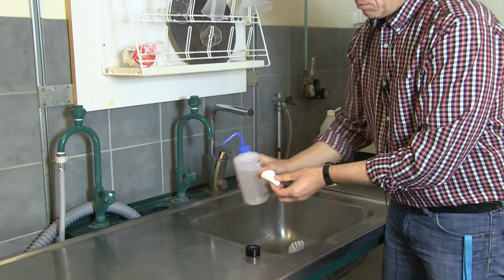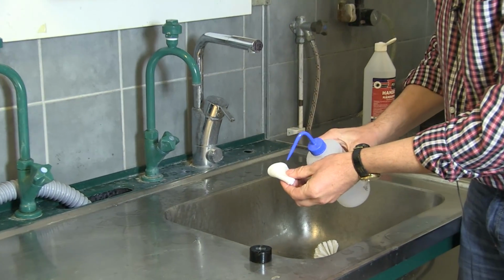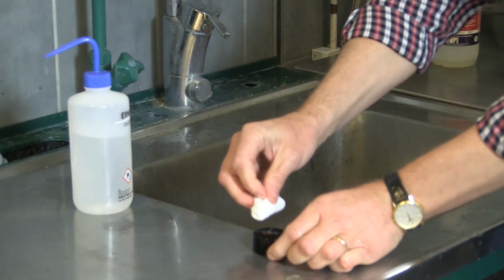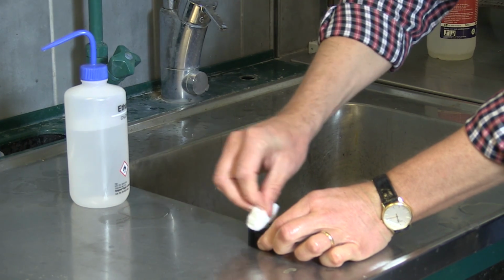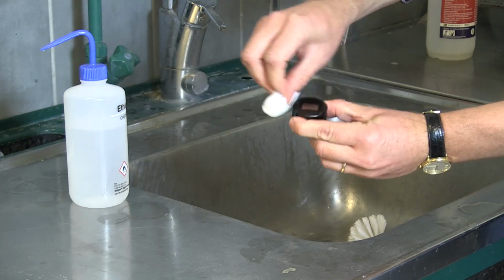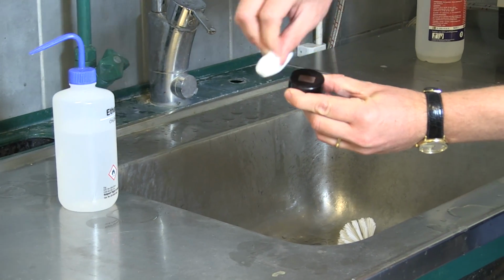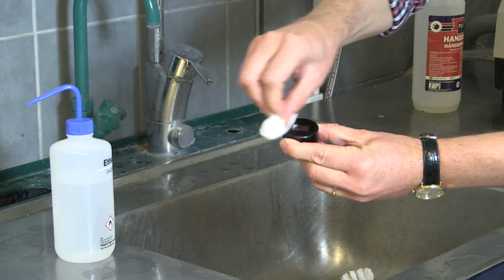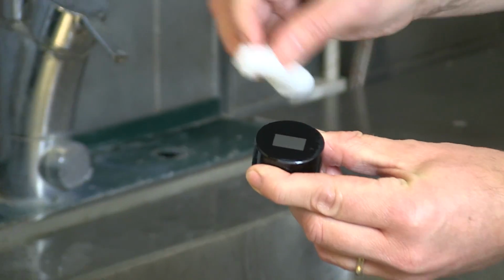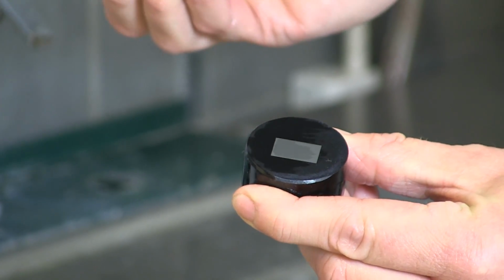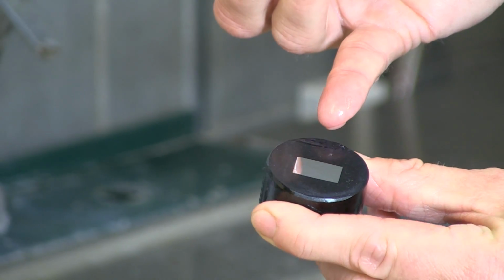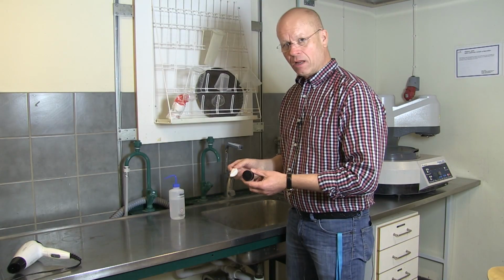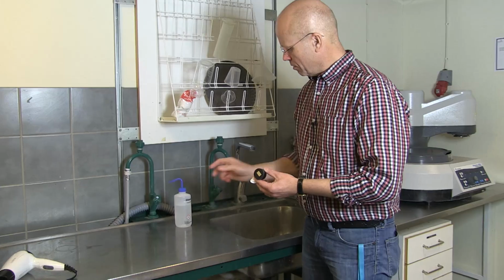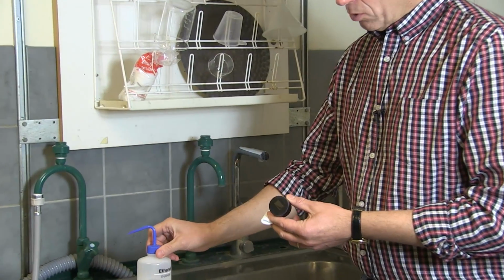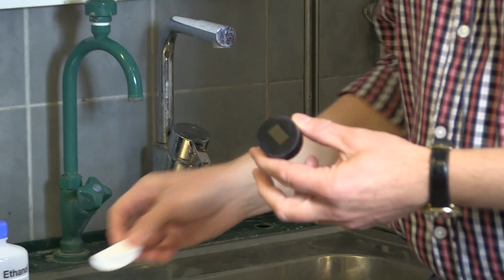I wet it with ethanol, and then I wipe the surface to remove silicon dioxide residuals. When I wipe it with ethanol and leave a thin layer like that, it evaporates quite quickly. So personally I prefer cotton and ethanol, but I will show you an alternative method as well.